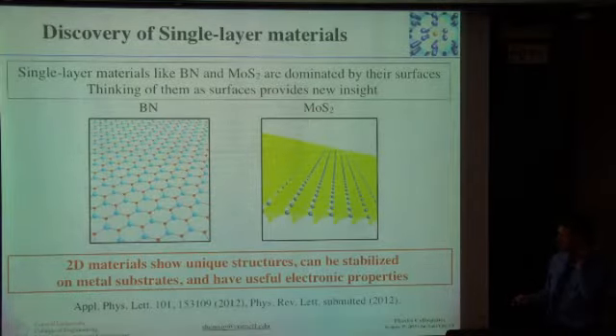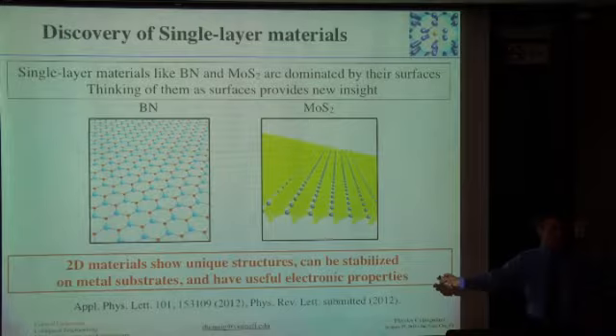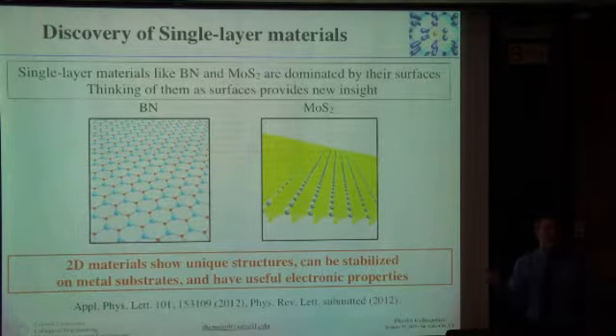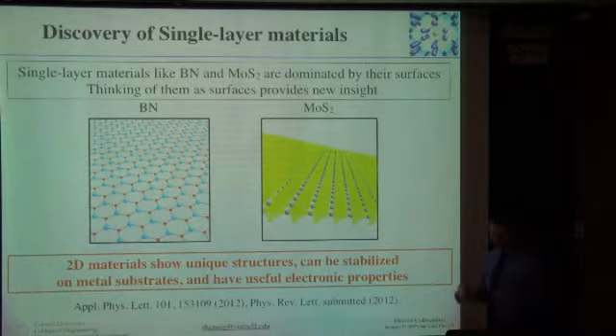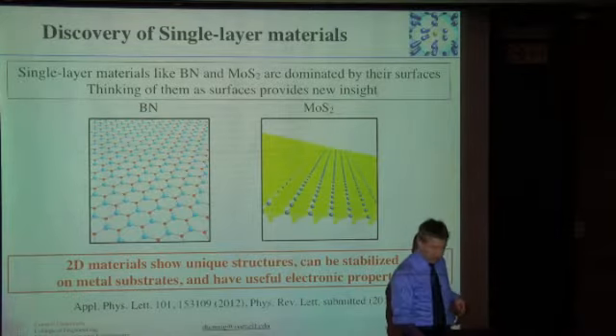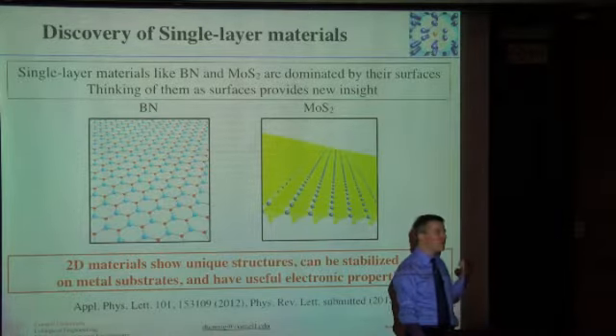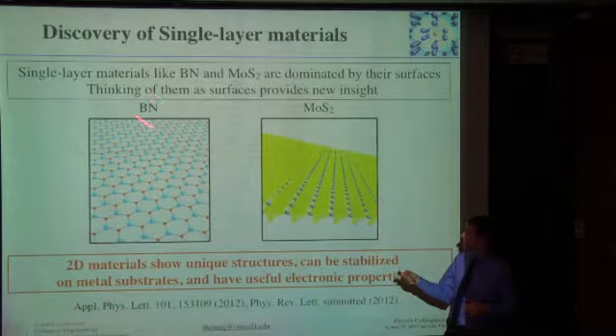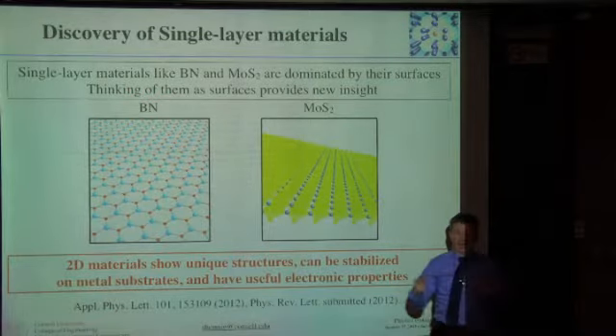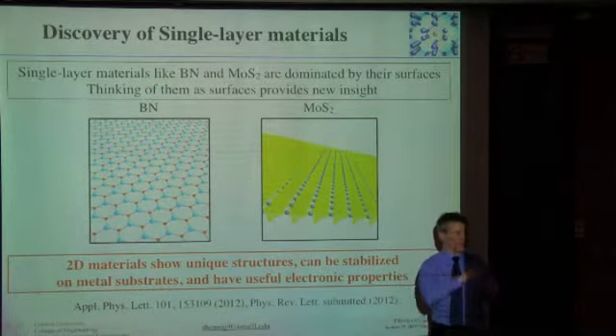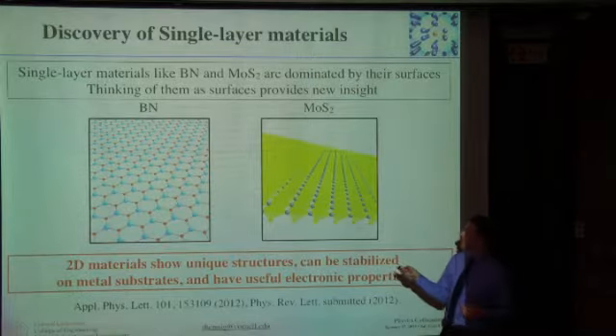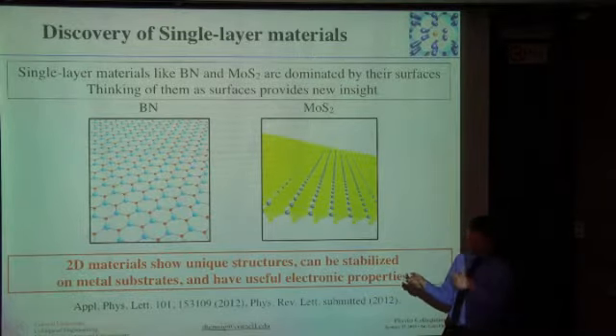We're interested in looking at what other 2D materials are out there. Just because we have those few, graphene, boron nitride, zinc oxide, silicon carbide, and molybdenum disulfide, doesn't mean that's the whole end of it. We want to really have a full spectrum of them. And so what we did is we looked at materials which have similar 3D crystal structures as boron nitride, which is wurtzite and zinc blende, so the diamond-like structure with atoms, either the cubic or hexagonal diamond, and it's just there's 2 atom species in there instead of just the